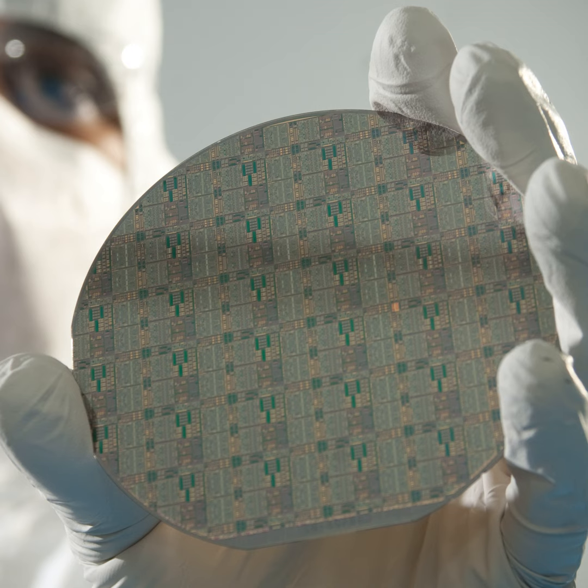I've mentioned diamond a few times here. So extrinsic to the device itself, we're using diamond on both the top side and the bottom side. The top side will be accomplished through low temperature growth on the surface of the transistor. And on the bottom will be the bulk diamond from Diamond Foundry that'll be bonded to the backside of the transistor using a very thin, very low resistance bonding process. So between the two of those, they're effectively wicking the heat away using the world's highest performance material, which is diamond.